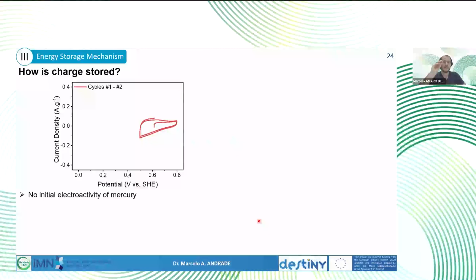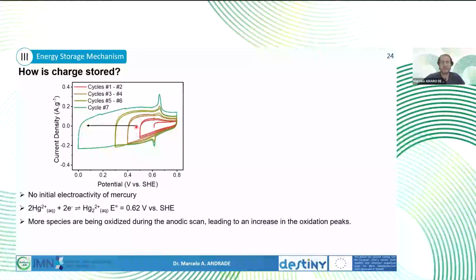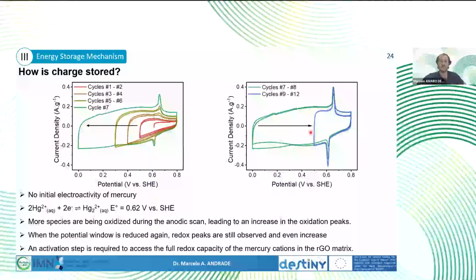And now, from the electrochemical point of view, how is charge stored, right? We understood mass loss, we understood mass variation. Mercury is moving in the electrode. If we start cycling with a limited potential window, we do not see the mercury redox happening. But when we expand this potential window down to 0 volts versus hydrogen, the redox peaks of mercury start appearing. Then if we shrink back to the original voltage window, the peaks remain. So basically there is some sort of activation of this mercury that is present since the beginning. It's not electroactive unless you go down to 0 volts versus hydrogen.